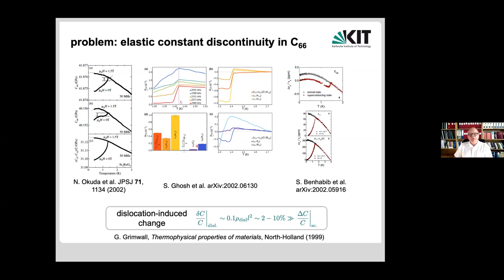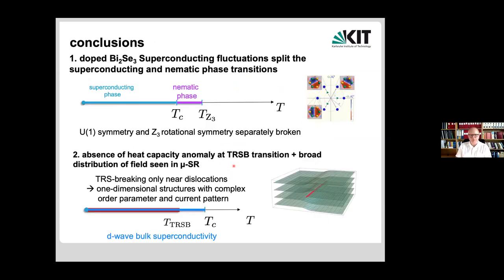And if you look at, for example, an elastic wave that goes with a C66 symmetry to the system, and it couples to a dislocation with very strong strain fields, you would mix in other symmetries and you could inherit the jump that you have in the trivial A1g channel in the system. Maybe too constructed, maybe it's realistic work. We need to find out in more detail whether this is the right explanation, whether our theory can hold up to this one experimental objection that I see with this scenario.